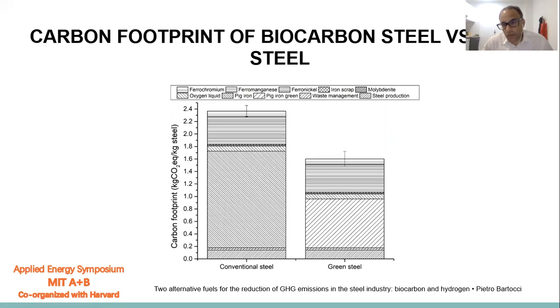In the final steel production, there is a higher emission for conventional steel, because as we say, when we come to the combustion of the final product, coke has important emissions of greenhouse gases, while biomass doesn't emit almost carbon dioxide, because we release what the biomass has previously absorbed during its growth. So the actual reduction of the total emission is about 31%, which is interesting.